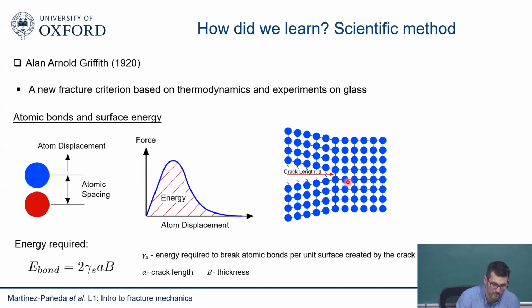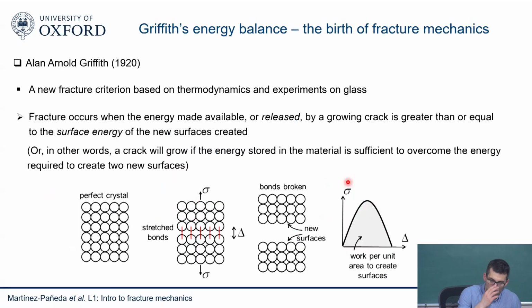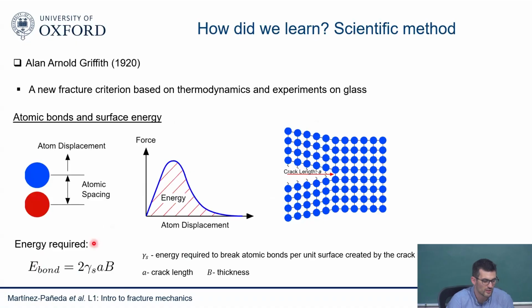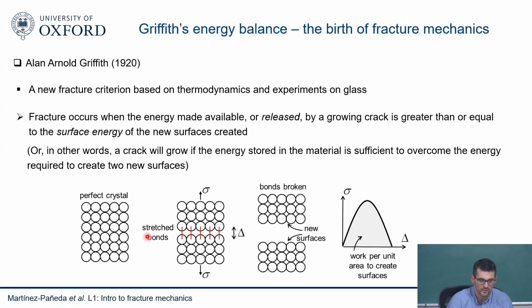The energy has to go somewhere, and there seems to be an energy required to separate atoms apart. So the idea was, in order to make a fracture process consistent with thermodynamics, again, the energy cannot just disappear. Energy must be transferred from one place to the other. So he thought, for fracture to happen, the point at which failure will happen will be when the energy that is stored in the material, that is released from the growth of a crack, is greater than or equal to this energy here. So you need this energy to create a crack. This energy must come from somewhere. So the energy that you're storing in your material, the energy that is going to be released when the crack grows, has to be equal to or larger than this bond strength.